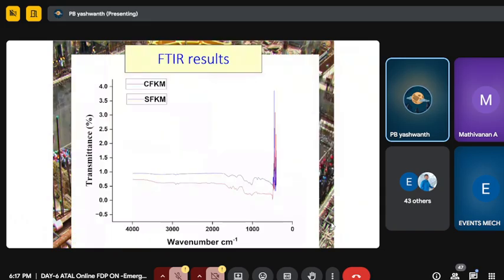The next set of experiments. Then come the FTIR results, where you have wave numbers. Every wave number has its own significance. Though they come from the same family of materials, fluoroelastomers, there is only a slight shift between the two materials. This Fourier transform infrared spectroscopy helps us understand which bonds, which fluorine bonds, which oxide bonds are crossing with the transmittance, the amount of light being transmitted. The spectroscopic result shows the significance of certain bonds, which play a vital role in giving high temperature resistance to that polymer.